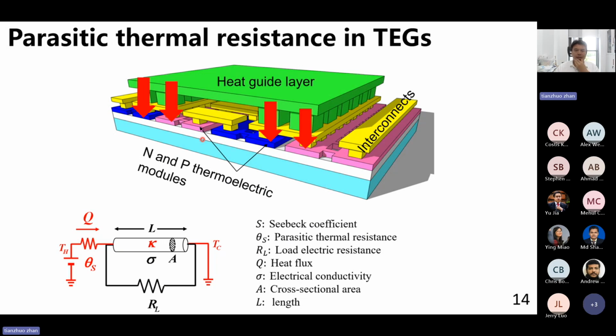We still have some problems if we want to further improve the performance of TEGs, because the parasitic thermal resistance in the TEG is very big. This is a 3D schematic diagram of the TEG. We can see that we have a silicon substrate and also a heat guide layer to facilitate the heat spread from the heat source to the hot side junction of all the thermoelectric modules. We know that only the temperature difference across the thermoelectric modules can generate power, and the other parts of the TEG cannot generate power and only waste temperature difference. So we need to decrease the parasitic thermal resistance in TEGs to improve the power density.